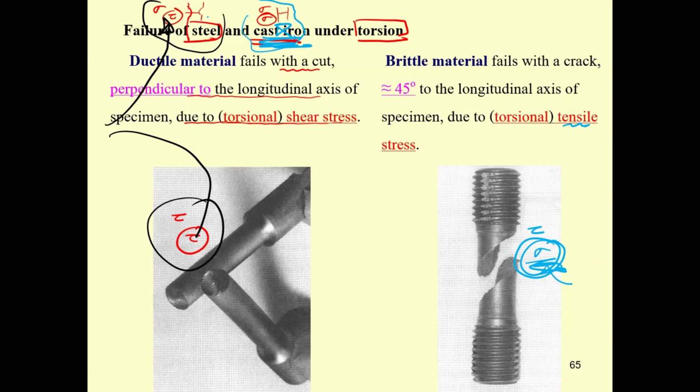Okay, and then steel, aluminum, they are ductile materials. They sometimes have the necking. The failure of them is due to the tau, and that's why ductile material must use the maximum shearing stress failure criteria, or the maximum octahedral shearing stress failure criteria, to predict their behavior. I would link this one to Mr. Angelo because he took Advanced Mechanics of Materials and he studied the failure criteria, and the result from material testing can link into what you have learned.